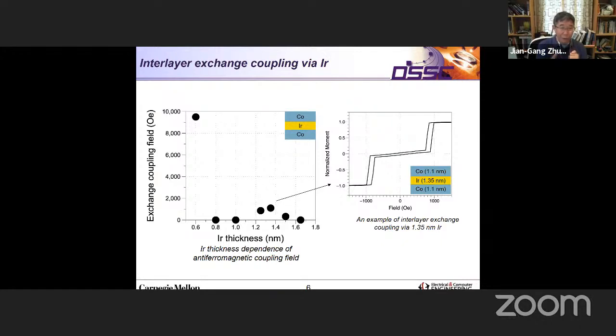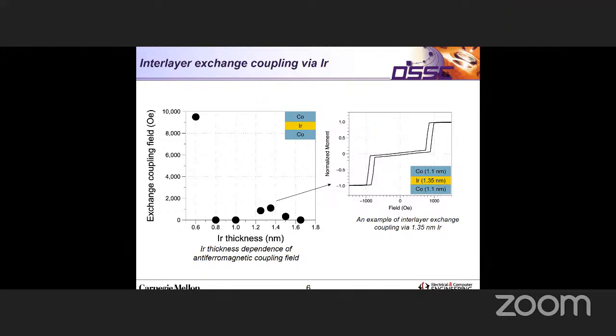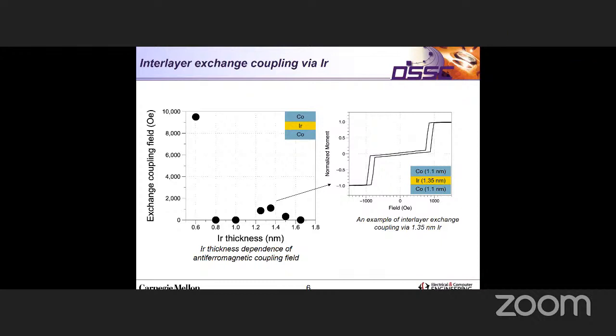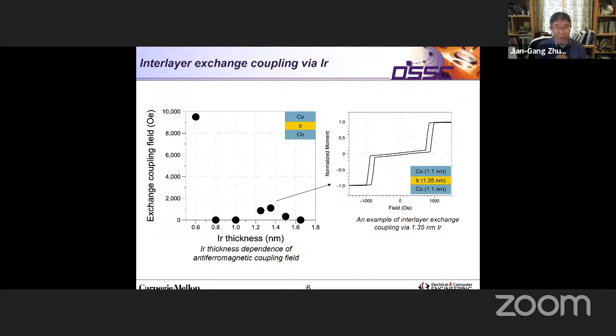So it's oscillatory. So it oscillates. Usually you see a few more peaks, but the thicker, the smaller the peaks, and it decays really fast. But it is oscillatory. I see. And then I think because you are relying on spin orbit torque coming from spin Hall, you want this thickness of iridium so that you have enough charge current flowing through. Correct. I see. Yeah. Great. It's really a compromise of the two.